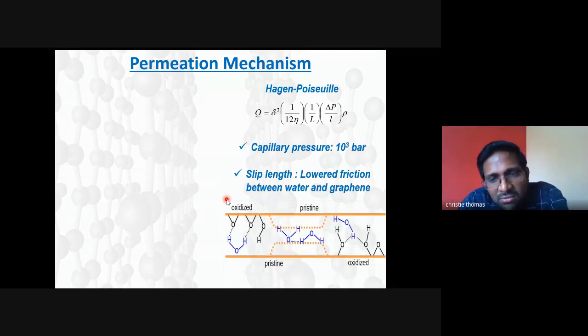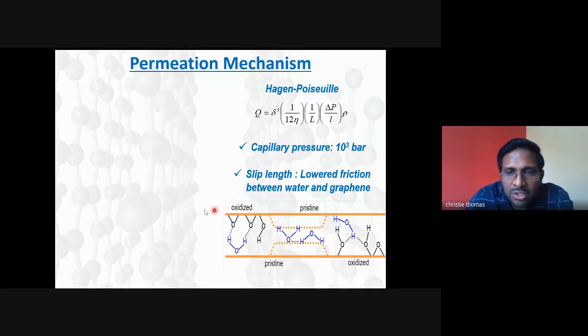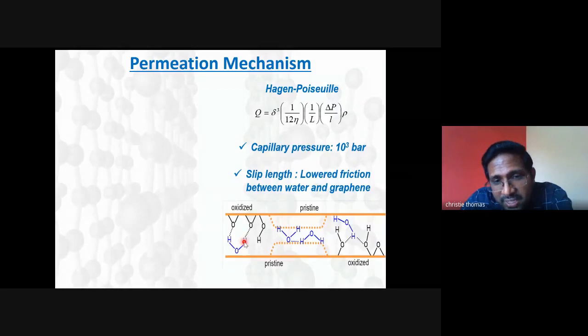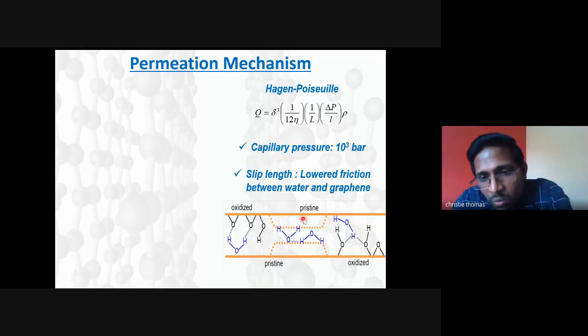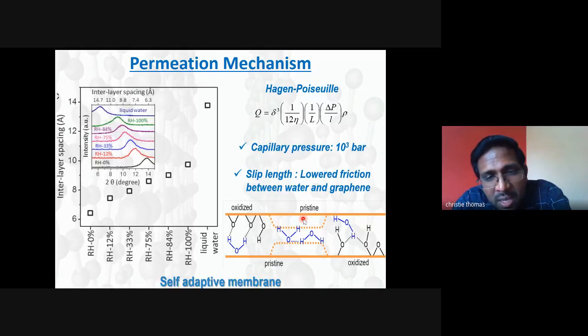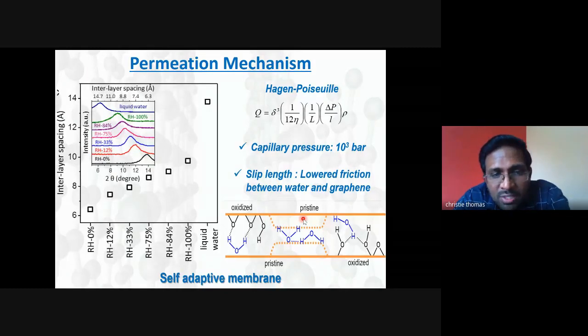So you can imagine it as two graphene oxide sheets with oxygen functional groups. These oxygen functional groups act as spacers. That means they control the d-spacing, or the interlayer spacing, between two graphene sheets. The proof for that comes from this graph. This is basically the interlayer spacing versus RH.